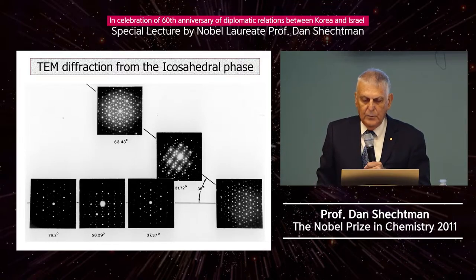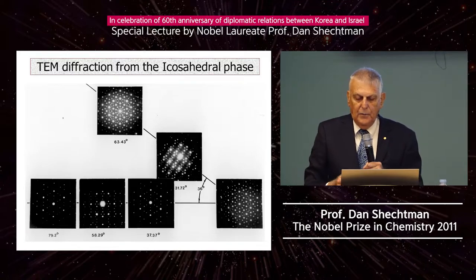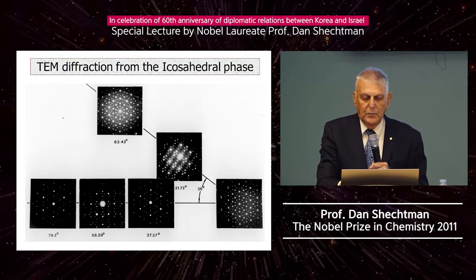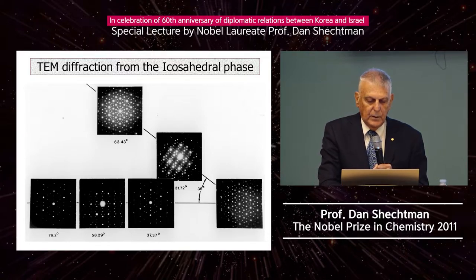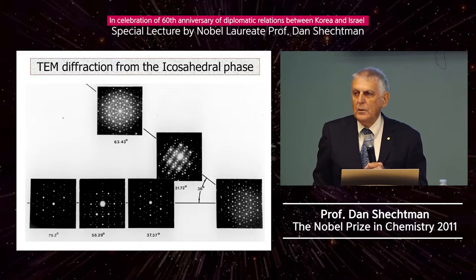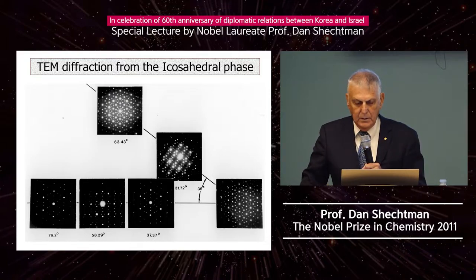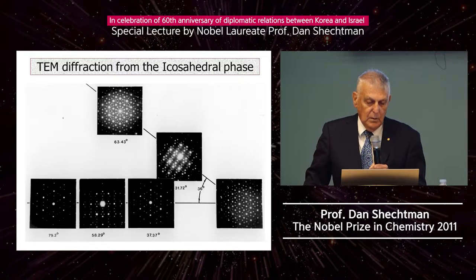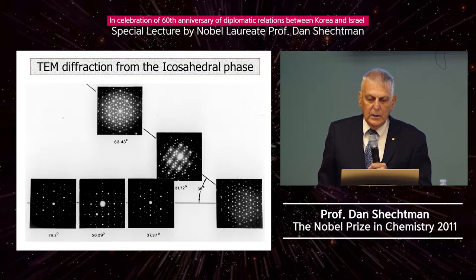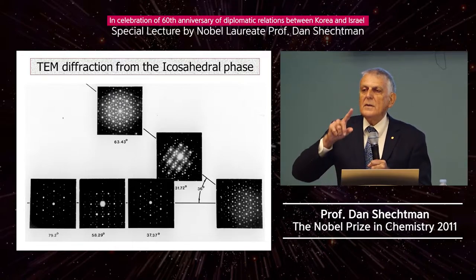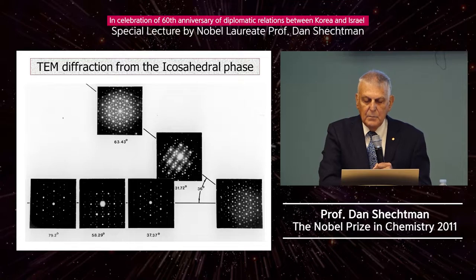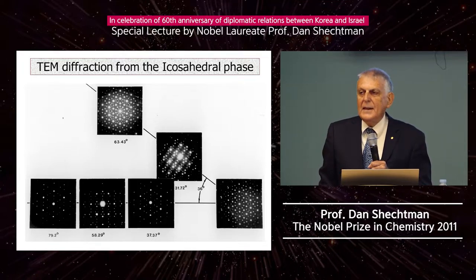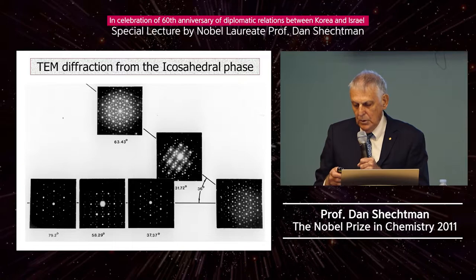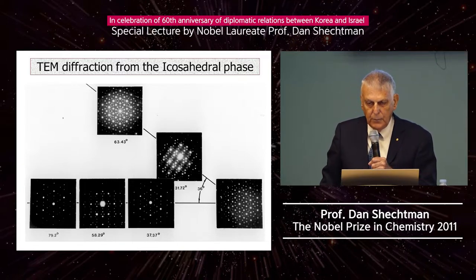And if you look from the down right, you see five-fold, two-fold, and five-fold again, and sideways, five, three, two, five. Now, two-fold and three-fold are allowed in periodic materials and also in quasi-periodic. Five-fold is not allowed. But why did they call it icosahedral phase? Because this order and the angles between the orientations has an icosahedral symmetry. I will talk about icosahedral symmetry in a few minutes.